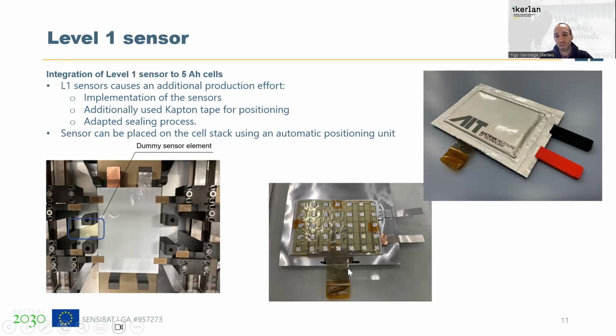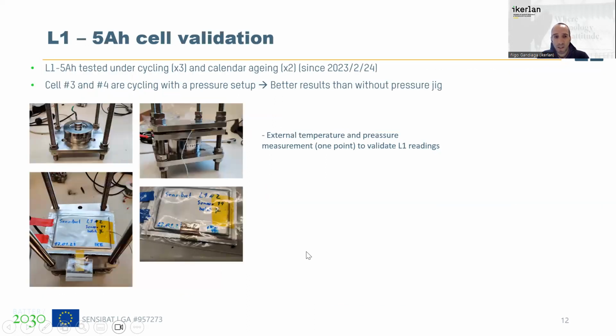Okay. We also needed to adapt a little bit the sealing process of the cell, because we put here a glue to seal the cell perfectly and not to have leakage of electrolyte from the inside to the outside. And this is something different from the one that we are using on the tops of the cell. Okay. We started this validation with 5 ampere-hour cells. So we tested 3 cells with a cycling protocol and 2 cells at calendar aging protocol.